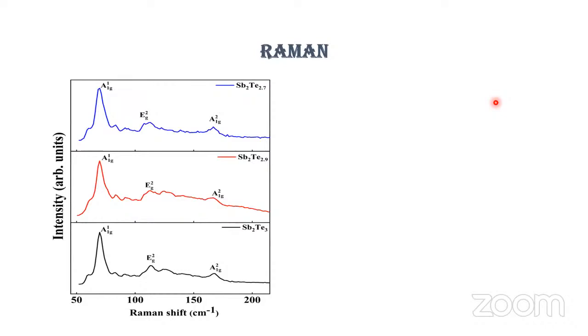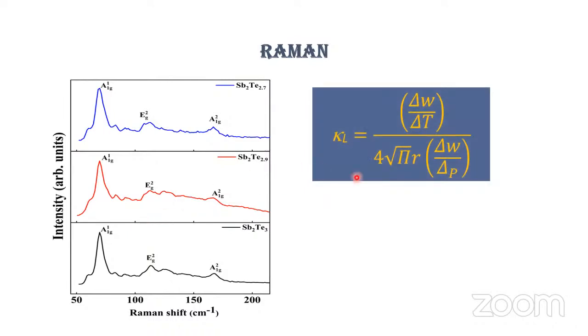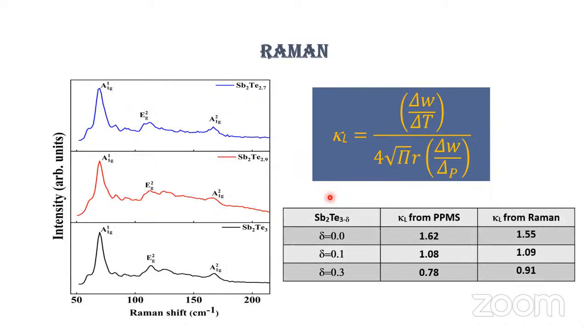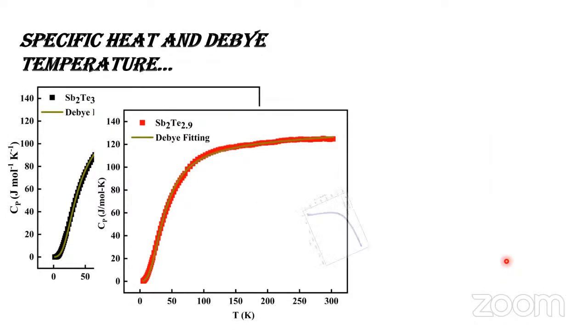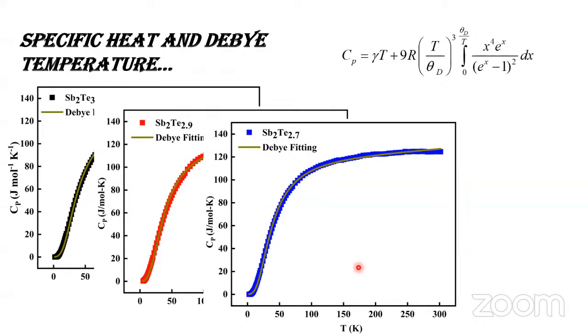For further verification of phase, we have carried out Raman spectroscopy measurements. From the room temperature Raman spectroscopy measurement, the single-phase nature of all the samples is proved. And we also have temperature-dependent and power-dependent Raman spectroscopic data. Using this equation, we can estimate the thermal conductivity value from Raman. In this table, you can see the thermal conductivity from PPMS data and the thermal conductivity from Raman data, and these two are consistent and comparable. For further study, we have also carried out temperature-dependent specific heat measurements, and all the data are fitted with the well-known Debye equation.